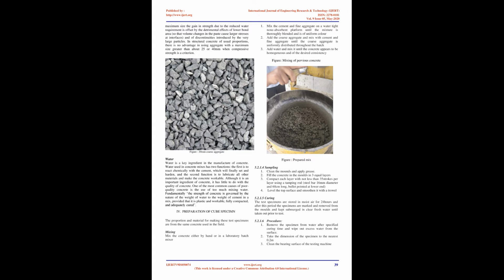Bond is affected by the physical and chemical properties of aggregate. For good development of bond, it is necessary that the aggregate surface be clean and free from adhering clay particles. The determination of the quality of bond of aggregate is difficult and no accepted tests exist. Generally, when bond is good, a crushed specimen of normal strength concrete should contain some aggregate particles broken right through, in addition to the more numerous ones pulled out from their sockets. An excess of fractured particles might suggest that the aggregate is too weak.